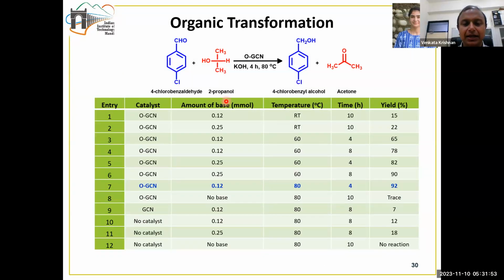Subsequently, we have utilized this as a catalyst for an organic transformation, the hydrogen transfer reaction, wherein we reacted 4-chlorobenzaldehyde with 2-propanol in the presence of our catalyst under certain conditions, which are illustrated here, to obtain 4-chlorobenzyl alcohol and also acetone. So what actually happens here is that 2-propanol acts both as a solvent as well as a reactant, which makes it a neat reaction. This means the two hydrogens shown here combine with this CHO group to lead to the formation of this benzyl alcohol moiety.